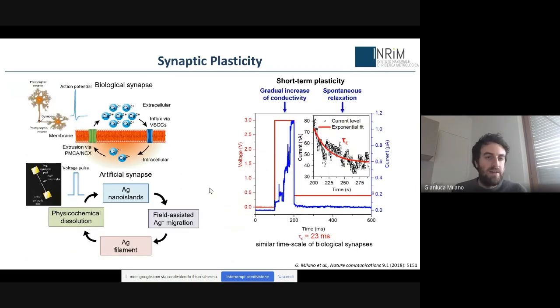So this is an example of what we have done in single nanowire devices. Without going into details, we can say that calcium ions play a key role. The influx and extrusion of this calcium inside the membrane of the biological synapse, after this synapse has received an action potential, is responsible for a change of the conductivity of the signal in between two neurons. And by emulating this process with silver ions, we can say that the field-assisted migration of silver ions can emulate the influx of calcium ions inside the biological synapse to form a silver filament that leads to an enhanced information transmission. And then we have a spontaneous physical-chemical dissolution of the filament that emulates the extrusion process of calcium dynamics.